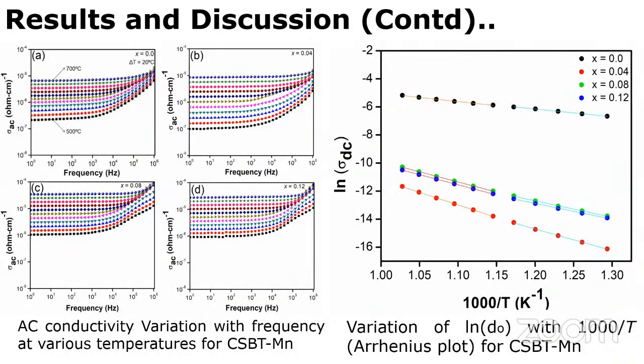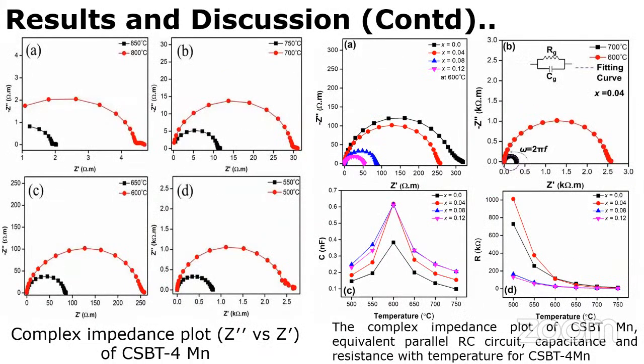Now moving towards the AC conductivity variation. AC conductivity also increased linearly and constantly. Now moving towards the DC conductivity graph, we can calculate the activation energy with the help of the DC conductivity graph. In the complex impedance plot, we can see a single semicircle, which is attributed to a single relaxation process, and the impedance is primarily due to the grains only. The capacitance was the highest for the CSBT4 composition, and the resistance was also the lowest. CSBT4Mn was the best composition out of all the compositions studied.